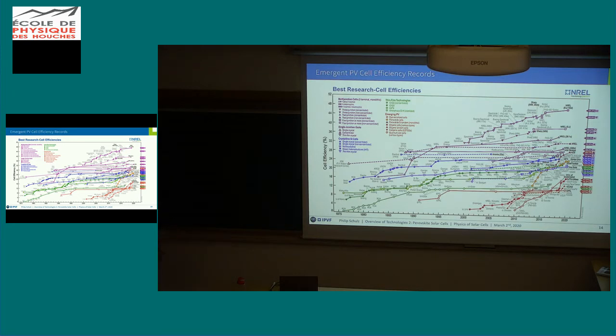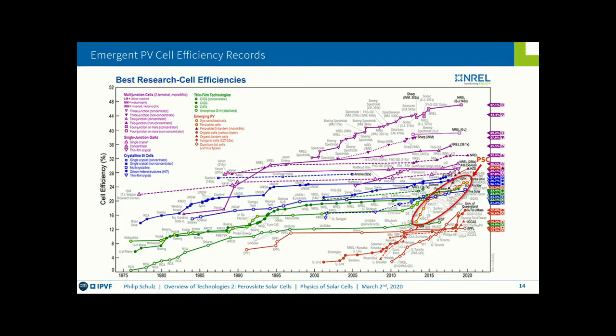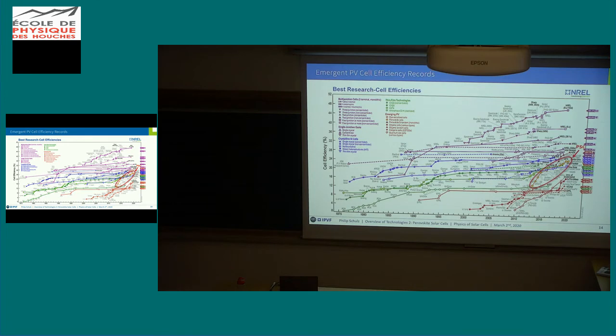We are here on orange on the emerging PV, and the perovskites starting out at what was about 12%, skyrocketed, surpassed their other thin film counterparts, except for thin film silicon, and are now at 25.2%. In tandem with silicon, earlier this year, 29.1% was reported by Steve Albrecht's group in Berlin at HZB. So this is really the axis, the trajectory that we are following.